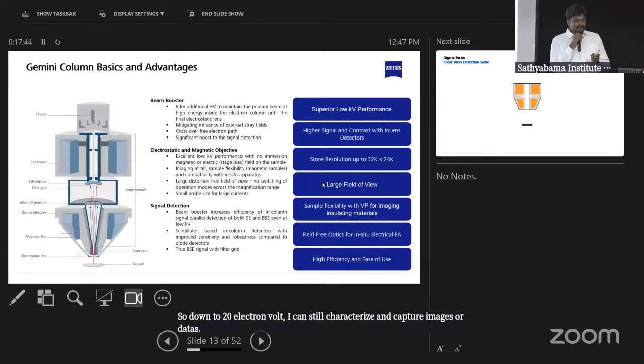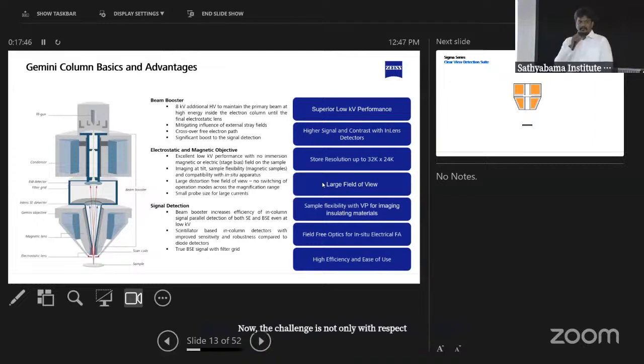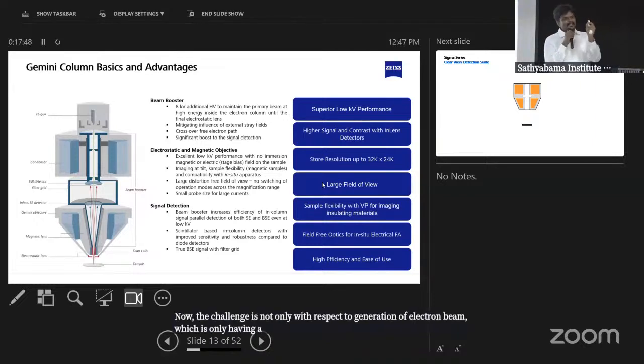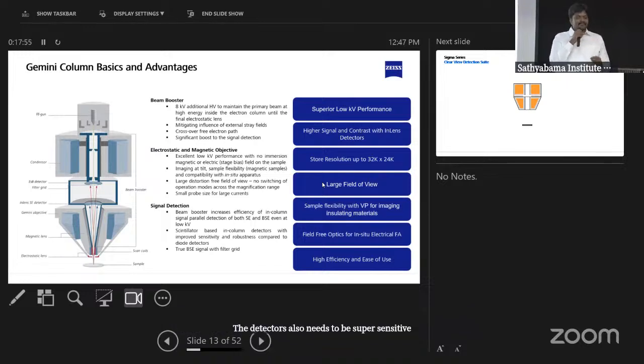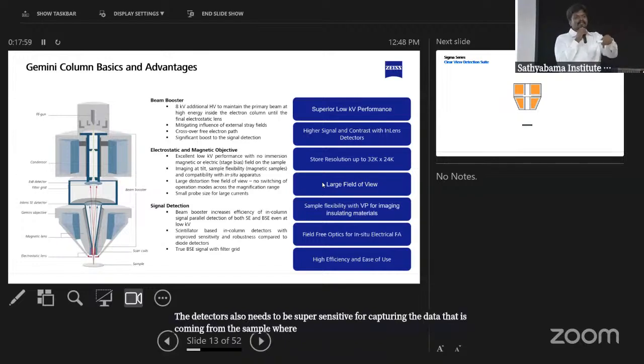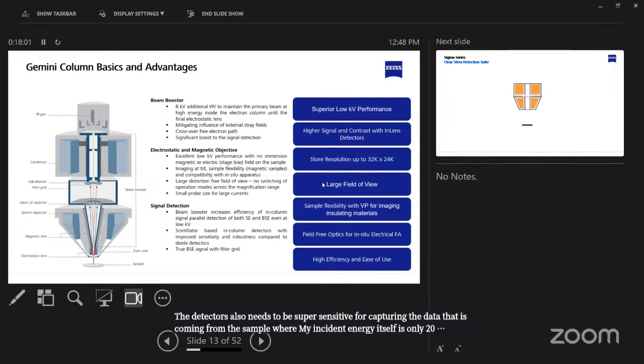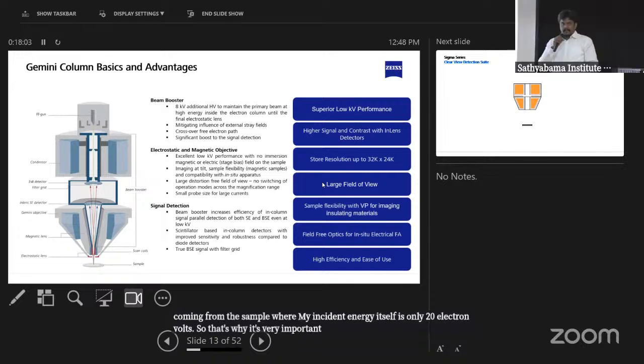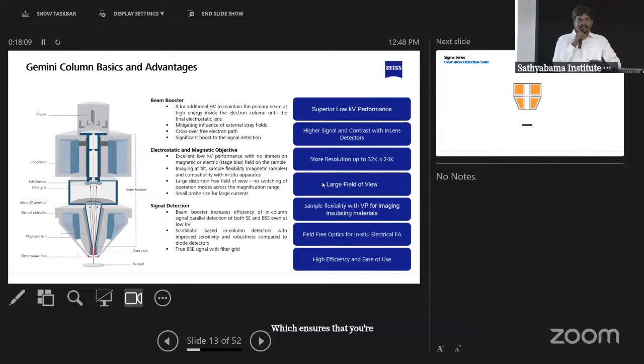Now, the challenge is not only with respect to generation of an electron beam which has only 20 electron volts of acceleration voltage. The detectors also need to be super sensitive for capturing the data coming from the sample, where my incident energy itself is only 20 electron volts. So that's why it's very important we have the most sensitive and robust detecting mechanisms, which ensure that you're not compromising on the data that you're capturing using your electron microscope.